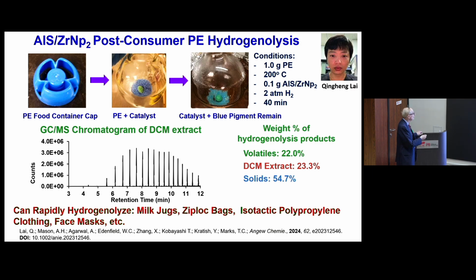So we took this, people said, oh boy, the pigment, the coloring in that plastic is going to kill your catalyst. It has no effect at all other than turning the catalyst blue. But it works very well, and this is just showing GCMS of some of the lighter weight fractions. And Qingheng was able to hydrogenolyze milk jugs, Ziploc bags, isotactic polypropylene, clothing, face masks. So the face mask he's wearing there, don't put it in our reactor because it'll be gone.